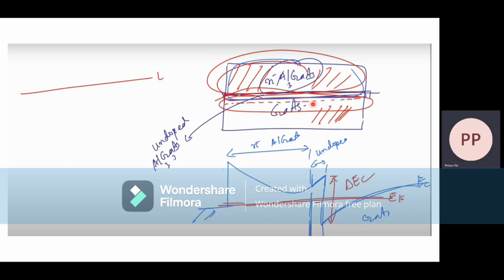So the band diagram, if we draw the band diagram, it will look like this. This is the Fermi energy level. It will look like this, and the valence band will also mimic it. Essentially, this is the doped N-minus aluminum gallium arsenide layer on the top. This layer is an undoped layer, a very few nanometers, maybe 5 to 10 nanometers, of undoped aluminum gallium arsenide, and this is the gallium arsenide layer. Of course, this is your delta EC, which is the conduction band discontinuity.